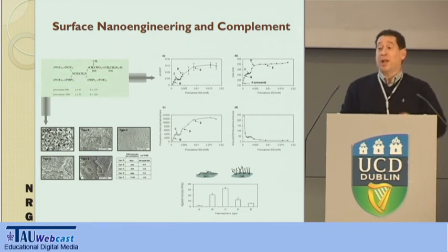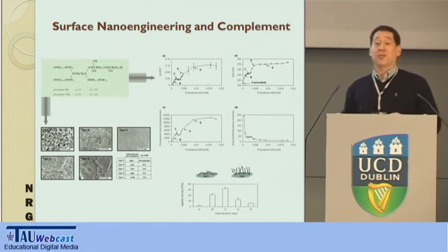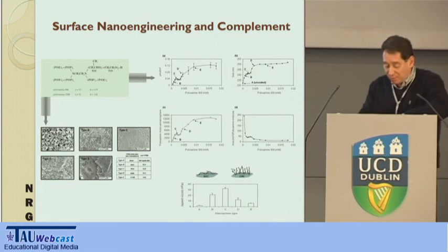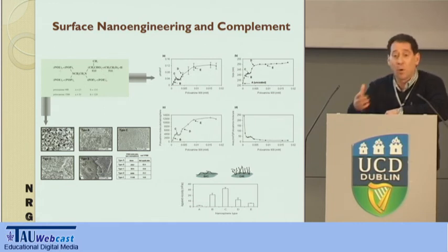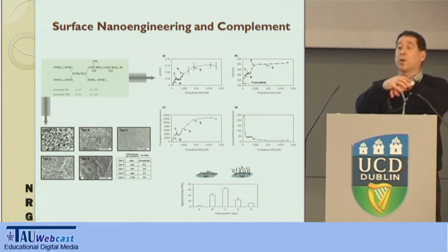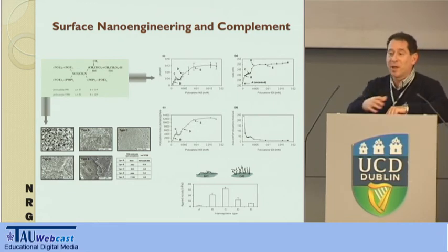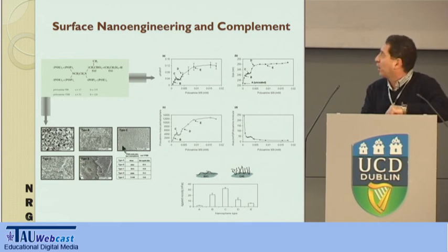So what I would like to illustrate now are some of these important properties in relation to nanoparticle engineering and some of the responses that you see, by giving you 2 or 3 very interesting examples that we published just last year or coming this year. Here we have used a polymer which is called poloxamine 908. You can see the center is polypropylene oxide because it's hydrophobic, it could sit on the surface of a hydrophobic particle like a polystyrene. And the good thing about polystyrene is you could get them in very near monodispersed preparations. And here we have used a particle of around 230 nanometer with a very low polydispersity.